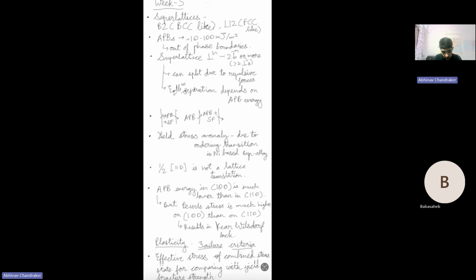In this, we'll continue with that by looking at dislocations which occur in ordered crystals, also called superlattices, because you have two different lattices which are meshed into each other. This is common in many alloys. For example, many BCC alloys have B2 ordered lattices. B2 basically is two different simple cubic structures which are meshed into each other such that overall they seem to form a BCC-like lattice, but they are ordered. So every atom has a specific spot which it will occupy. It will not occupy the position of a different element.